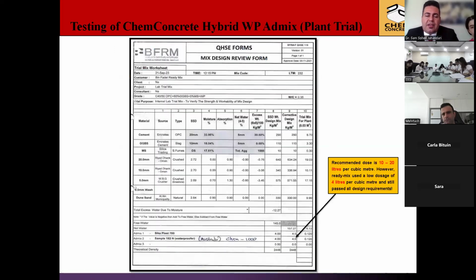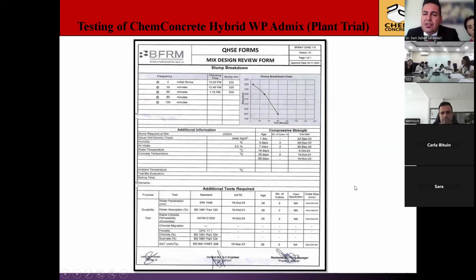And these are interesting test results from a ready-mix supplier in the UAE, in Dubai. The recommended dosage of our product is normally around 10 to 20 liters per cubic meter, but they used only 4 liters per cubic meter of concrete. What was very interesting was that they used less than half the dosage we recommend, and they passed all their design requirements.